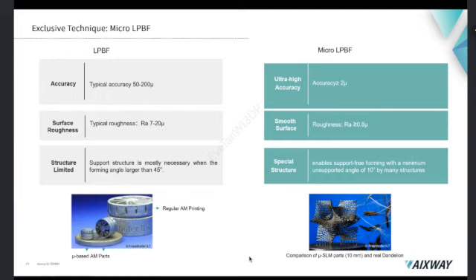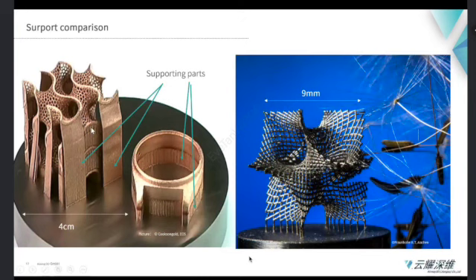Third, there is a critical point for micro 3D metal printing, 45 degrees. When the angle of a structure is less than 45 degrees, it is necessary to add supporting parts to achieve a solid printing. Our micro 3D metal printing enables support-free one-step forming with a minimum unsupported angle of 10 degrees for many structures. As you can see in this comparison, conventional printing requires a lot of supports, like here and here and here, while with the micro-LPBF, we can print similar structures without any supports. As a result, of course, the material waste and the post-processing are also greatly reduced.